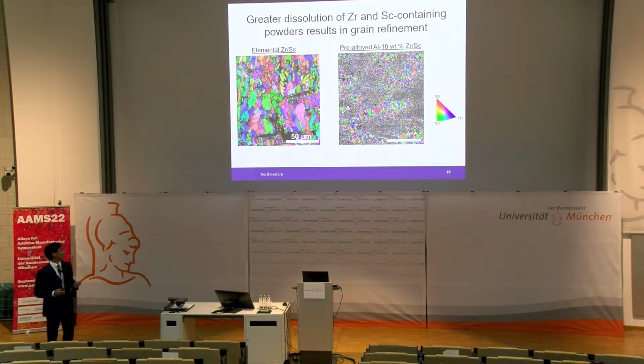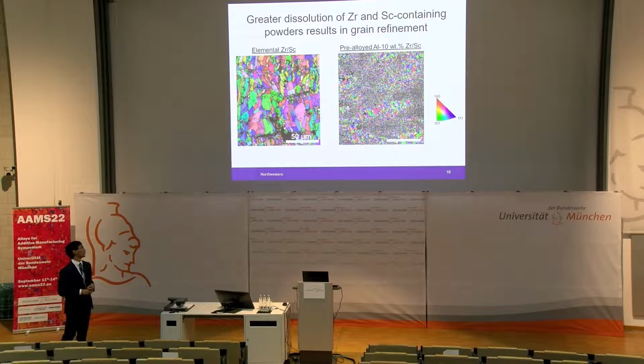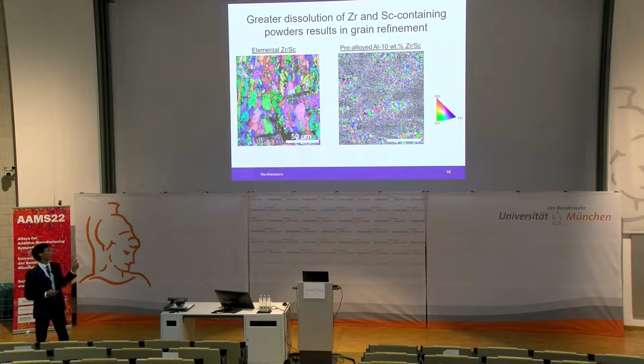Now, as a result of this greater dissolution, what we see is that there's greater grain refinement in the alloy containing these pre-alloyed 10% zirconium powders. This is, of course, due to the fact that we're able to dissolve more zirconium during melting, which is able to nucleate fine L1-2 aluminum 3 zirconium precipitates, which can then nucleate fine grains. And when we use elemental zirconium scandium powders, we only saw this grain refinement in the vicinity of these undissolved particles.